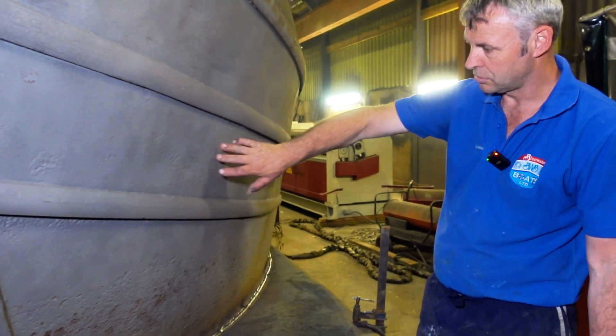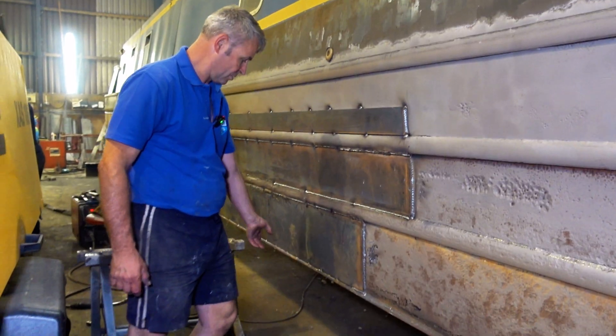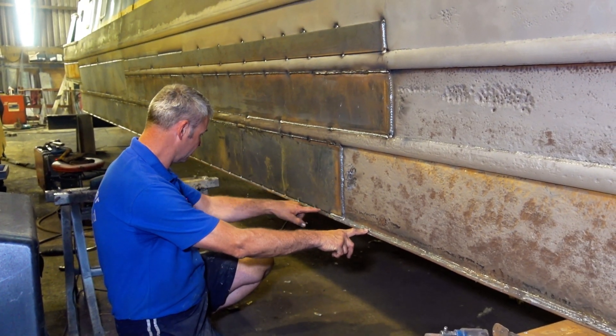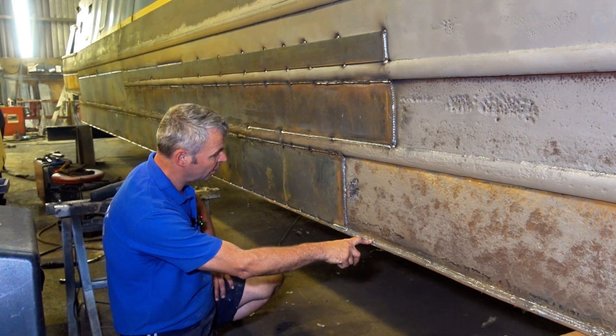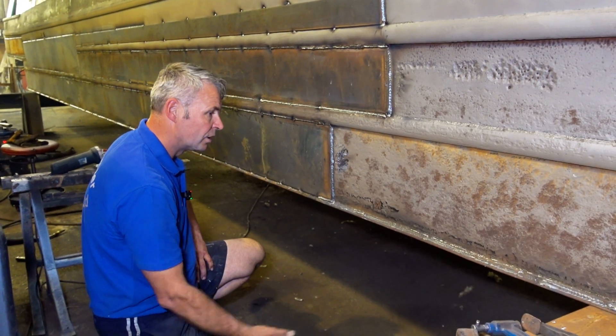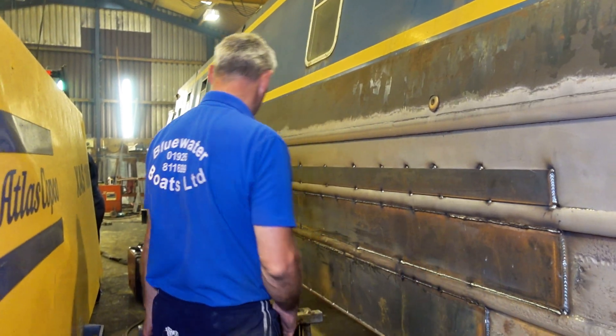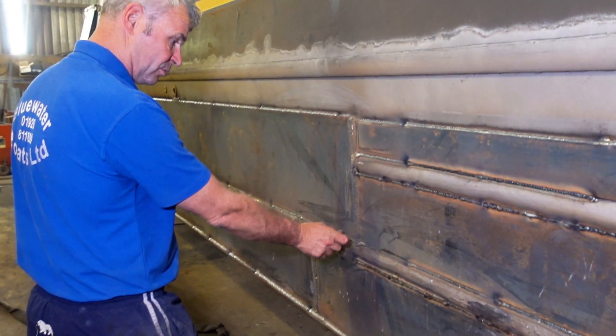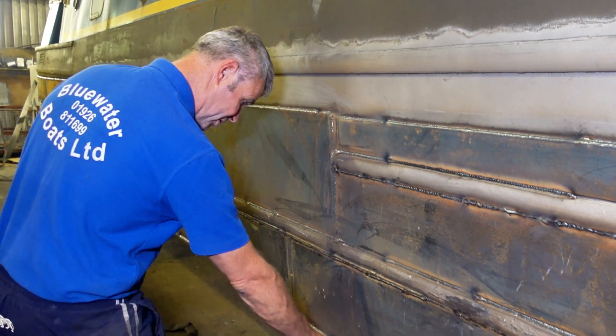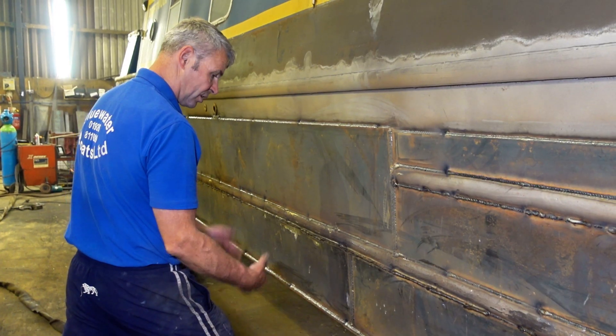You can see the pitting above the waterline is not too bad — it's all fine there. We've put new fresh six mil steel all on the sides. Where there are joints in the plate, we'll weld downhill in there just to keep the heat off the inside of the boat. This plate we put up against there and welded down as well. And if you look further along, you'll see where we've put a vertical weld to cap the two plates together. A lot of the heat in this one is into the rubbing strip, which protects and keeps a lot of the heat from the inside.